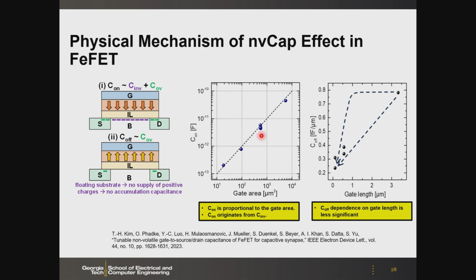So we verified this mechanism by some measurements. First of all, if this is true for the on-state, the on-state capacitance should be proportional to the gate area, which is verified by the experiments here. And then the off-state seems to be related to the overlap length. And then depending on the gate length, then the C off is proportional to that. So then at least from the measurement, this supports this hypothesis.